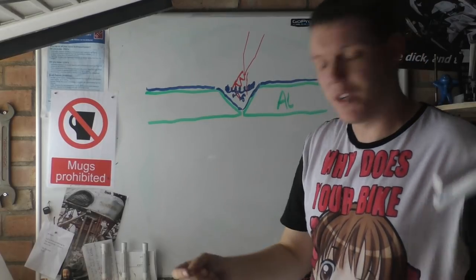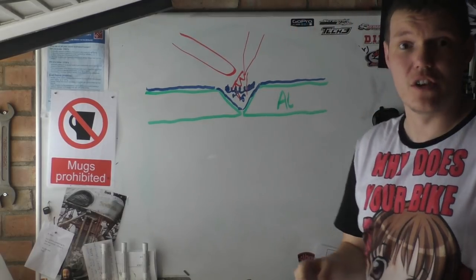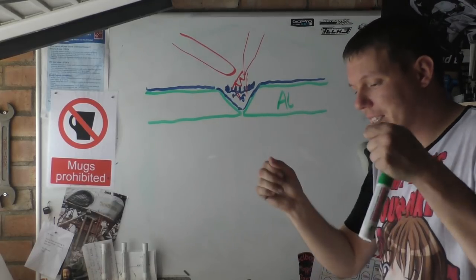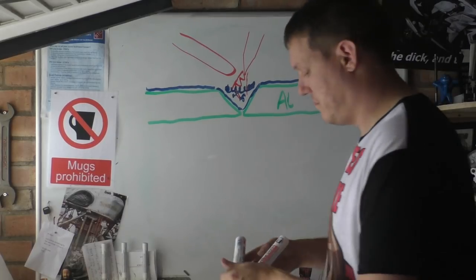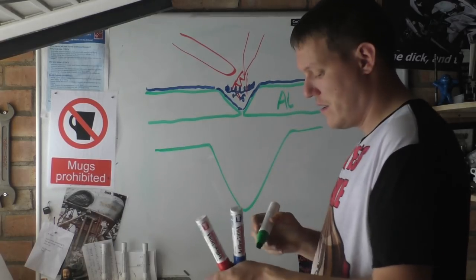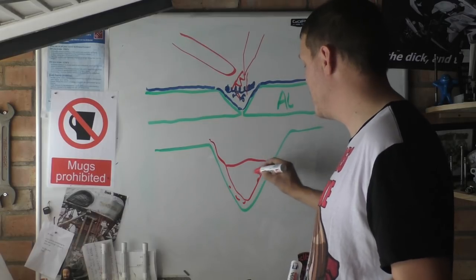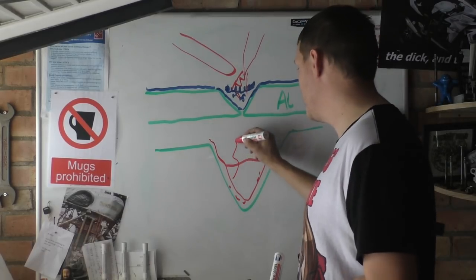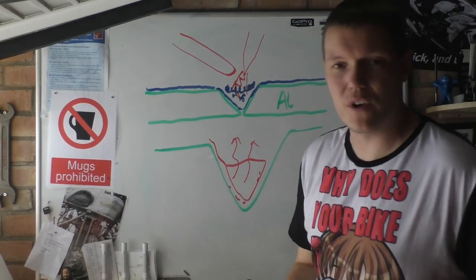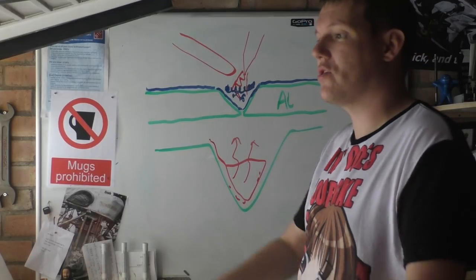When you add some filler rod in, that's got shit on it too. Most people clean the welds but a lot of people don't clean the filler rods. It's a chasm and you're going to drop new aluminum in it, which means that you are going to trap shit in it. But because it's still molten this is going to try and float in it. Basically it's inclusions, it makes it porous, it makes it horrible. So we are trying to stop stuff from the outside world getting in, the air and stuff, but also the shit that tries to boil off.